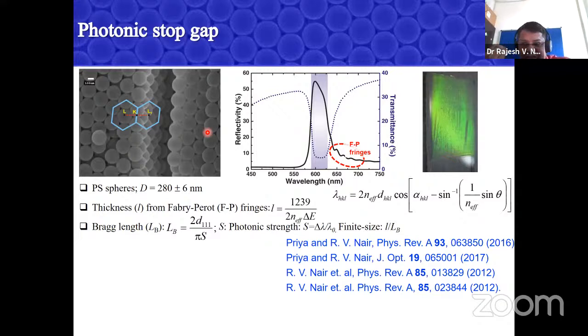And when you say fabrication, not by SEM picture, but by the optical response these samples should give. So this is one of the pictures we have, and then we grow the samples. And how do you know whether my sample has a frequency gap or not? So the typical experiment, what everybody does, you measure the reflectivity of the light as a function of wavelength. So I measure the reflectivity on the y-axis as a function of the wavelength of the light which is incident